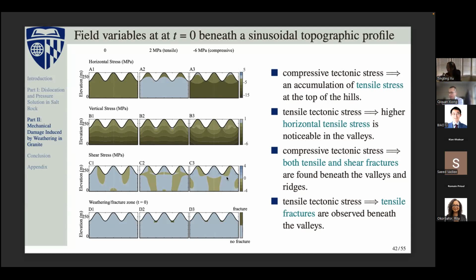in this simulation case. In contrast, for the tensile tectonic stress and compressive tectonic stress, the simulation conditions can open the crack under the valley, but with different patterns. For the compressive tectonic stress, it tends to open tensile and shear fractures, while for the tensile tectonic stress, it tends to only open tensile fractures. So that is at the moment before the weathering or the fracture propagation, before the weathering happened.